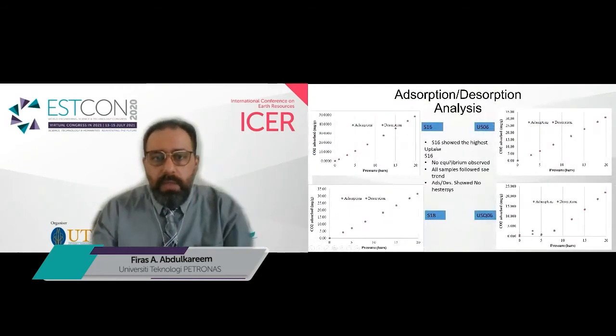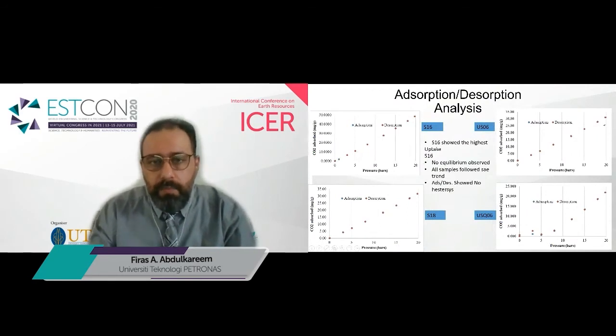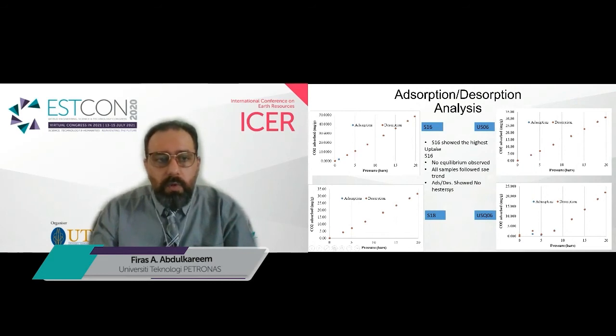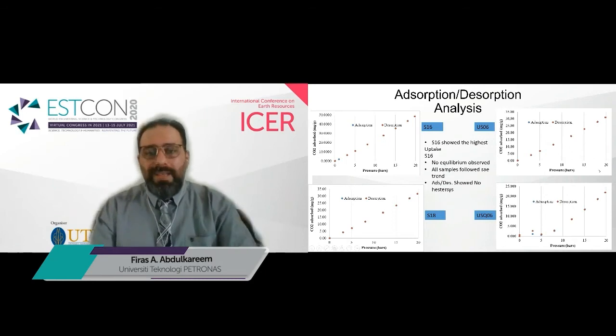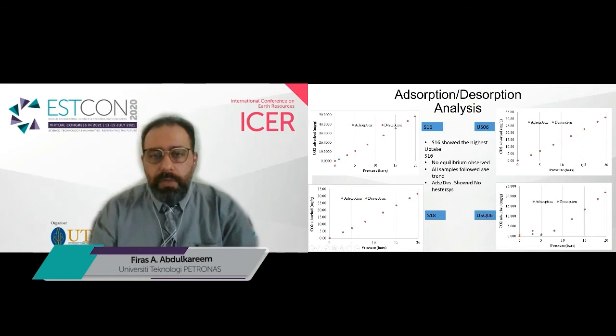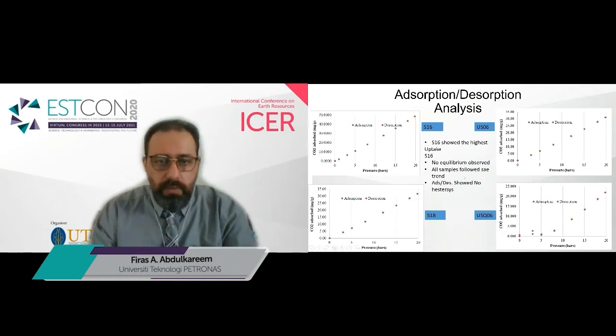But on the other hand, we can see that the absorption process has not achieved equilibrium, even at the highest pressures designed for this process. However, the absorption processes were conducted at almost 30 degrees, which is close to the supercritical temperature of CO2. But we were careful not to reach 70 bar, because we don't want to go to the supercritical phase of the CO2, and we need to maintain the CO2 within the gas phase. So as we can see here, the absorption and desorption were very similar at higher pressures, and not similar to what we obtained from the nitrogen BET at very low pressure. It means that a pressure drop can be overlapping the shape of the pores.